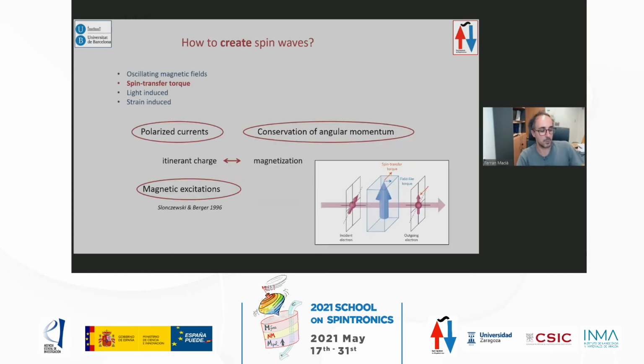Okay, maybe using a magnetic field was the way we all knew and everyone might guess, but there are other means to create spin waves. And one is the spin transfer torque. So we've seen that in the talks on Monday, and you'll see more about this on Friday. But the spin transfer torque is basically an exchange of momentum between itinerant electrons that pass and cross a magnetic layer or a magnetic material. So you have to have conservation of angular momentum, and what happens is that the material is kind of filtering the electrons. So there's an exchange of momentum, and on the one hand, you change the momentum of the spin of the itinerant electrons, and also if the magnetic material is thin enough, you can also change or modify the magnetization of your layer.